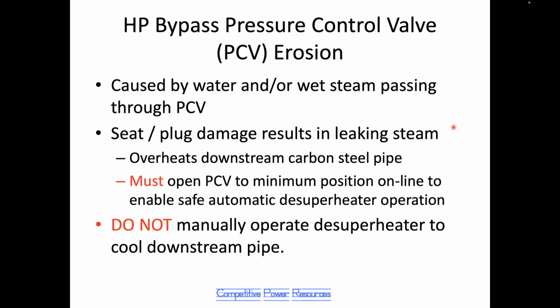When the seating surface damage gets bad enough, the valve begins to leak steam. Most of the time, there is a carbon steel pipe downstream of the pressure control valve. When this superheated steam starts leaking through the valve during operation, it overheats that carbon steel pipe. If you find yourself in that situation, the only safe alternative is to manually open the pressure control valve to its minimum operating position. And that will allow the desuperheater downstream to automatically come into service and cool the downstream pipe work.